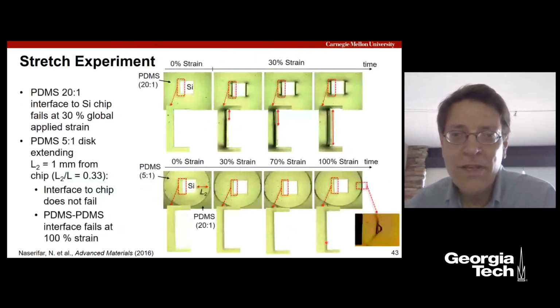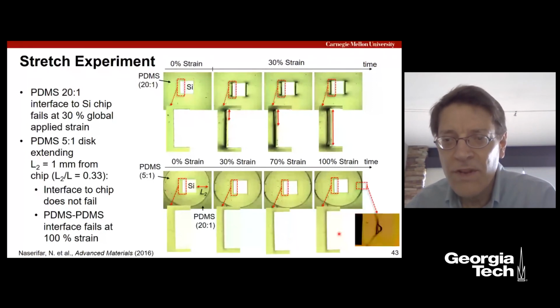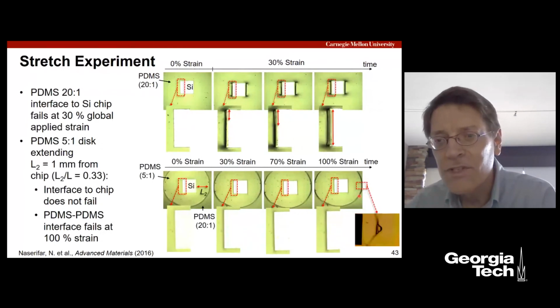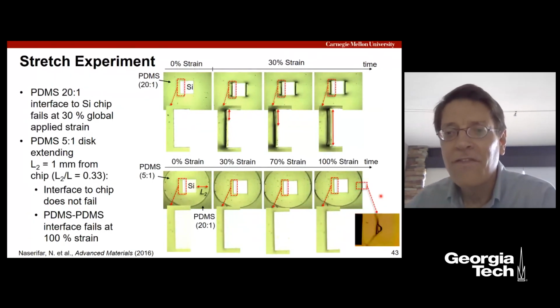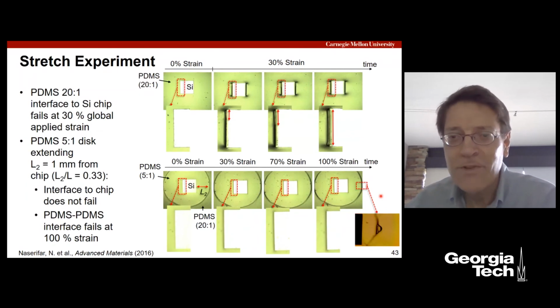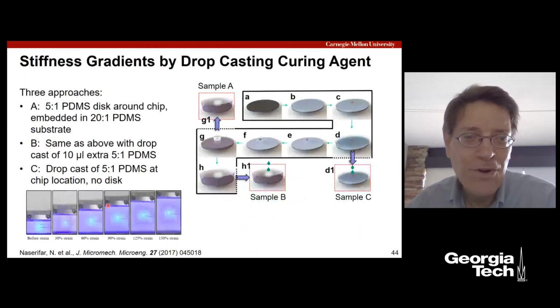And in fact, doing these validation experiments, pulling on chips with 20-to-1 PDMS, even at 30% strain, we were getting a delamination. And of course, if these were wired, the wires would just break. However, putting the 5-to-1 PDMS around the 20-to-1 PDMS, even up to 100% strain, we didn't get breakage. What was interesting is we started getting delamination at the 5-to-1 PDMS, 20-to-1 PDMS boundary, not at the chip boundary. So all of the interfaces are important.